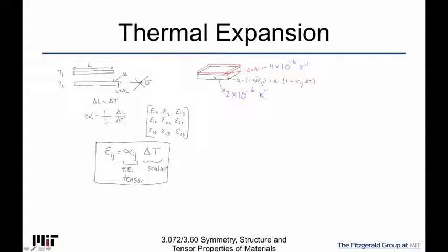I am going to produce a stress just from the fact that these two are cooling at different rates, but they're linked. They're linked so that they're not allowed, this top film, if this is much, much thicker. So the substrate thickness, let's call it H sub, is much, much greater than the film thickness. Then essentially the film is forced to go at the rate of the substrate. You can see here this has a higher thermal expansion. So it wants to shrink faster, but it can't.